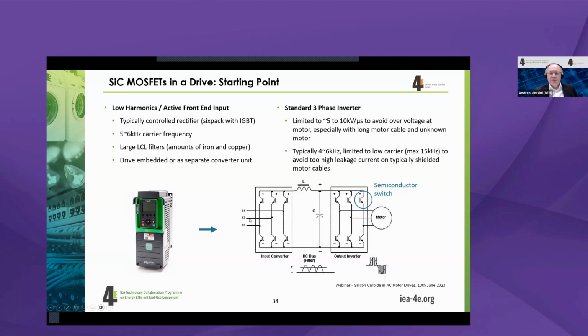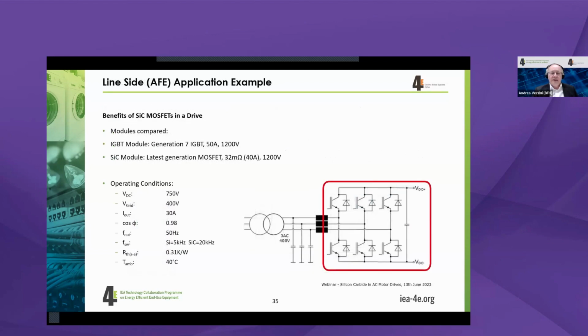This will allow you power flow in both directions, and it will allow you to also have very low harmonic distortion on the line side by having sinusoidal currents on the input. Typically, such low harmonics active front-end inputs operate at a carrier frequency of 5 to 6 kilohertz and additionally use large LCL filters for the line side. They're either embedded or as a separate unit. For an example of such an active front end, this is about a 22 kilowatt, so it's 400 volt line-to-line voltage, 30 amps RMS current.